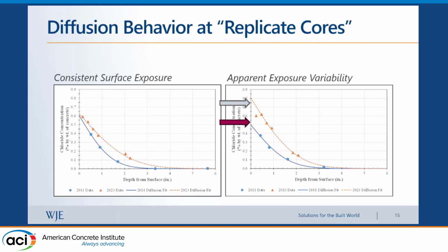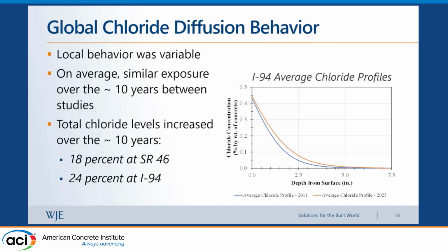But another approach is to consider that convection zone and consider the highest value here, or the peak value, as a surface chloride concentration, and account in your model for that convection zone affected by wetting and drying. So there are different ways to consider chloride profiles in your model input, and you have to be careful about how many of your profiles represent a specific condition, and you can make the evaluation whether it's worth considering in your model and how to consider it.